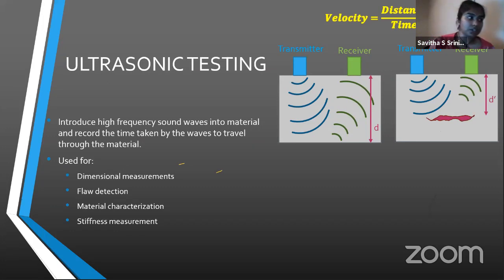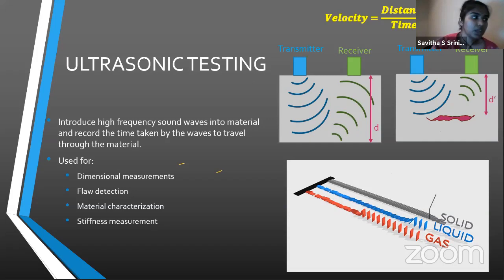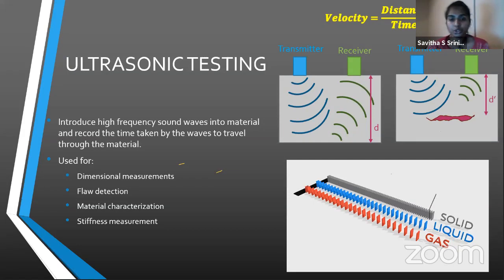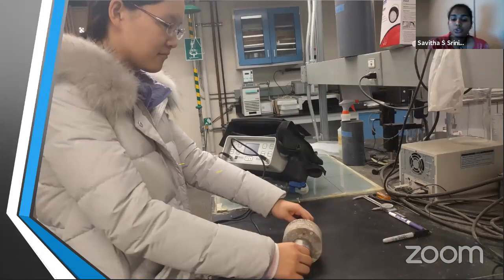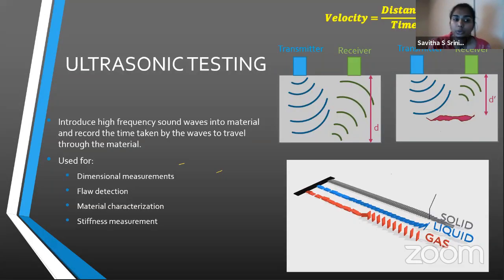The next one is you can also do material characterization. What this GIF shows is that a sound wave will travel faster through a solid material than it does through liquid or gas. So the denser your material, the faster your wave. So a higher ultrasonic pulse velocity is considered to be better because your material is denser or has fewer flaws. The other thing is ultrasonic pulse velocity has been shown to correlate very well with stiffness measurements. So if you are not able to do your modulus of elasticity test, or you don't have enough specimens to do it, you can use ultrasonic pulse velocity to get an idea of what kind of stiffness is expected from the specimen.